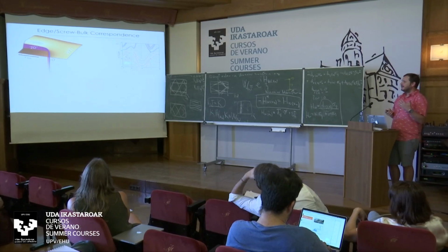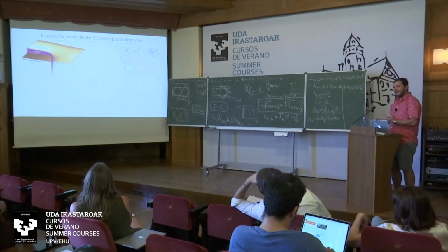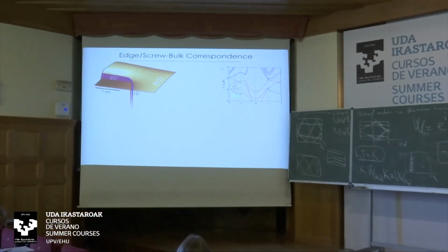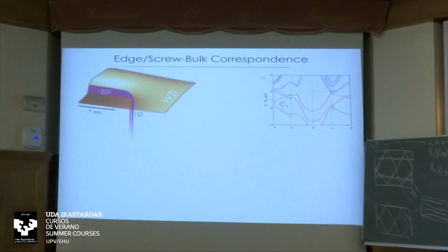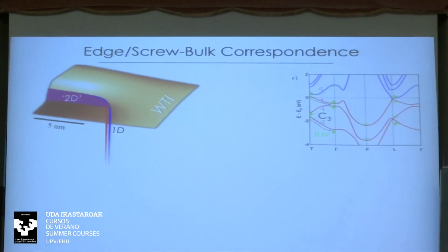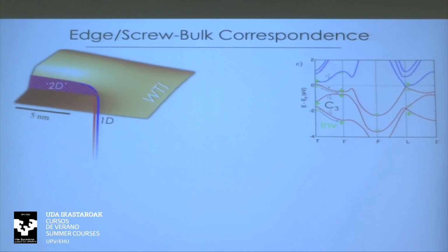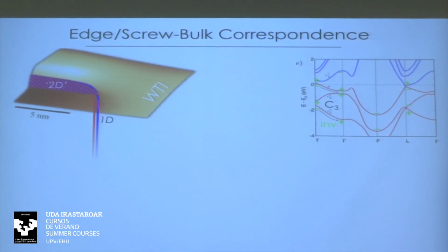So, looking from the theory side, the only true topological phase which is supposed to bind helical modes on screw dislocations to date is the weak topological insulator. In a weak topological insulator, it's the two-dimensional side facets which carry the helical mode.